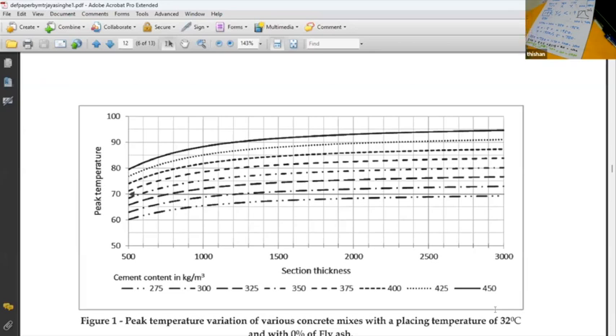So we do everything so that we start cool. When you start cool, you might find that the placing temperature can be dropped to about 26 degrees, because we have removed all the energy in the aggregates. So they are all cool, no energy in it. And we are using flaky ice, 40%. Then you get a cool concrete, and the placing temperature can be 26. If the placing temperature is 26, what is the maximum temperature? It will be below 70, because without cooling, at 32 degree placing temperature it is going to be around 74. And we reduce the placing temperature to 26. What will happen to the final temperature? Final temperature will be 68.